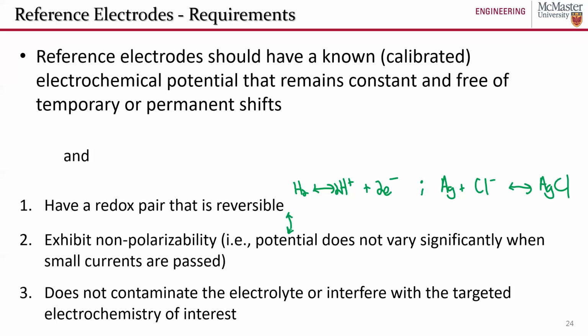Then you also want a reference electrode that is not going to contaminate your experiment. It's not going to contaminate your electrolyte. It's not going to contaminate your working electrode. It's not going to interfere with the targeted electrochemistry of interest. So say, for example, you're using a silver chloride reference electrode, and some of the chloride ions leach out of your reference electrode into your electrolyte. For something like platinum, chloride ions can interfere very strongly with some of the electrochemistry. So you just want to make sure that whatever reference electrode you're using is not going to contaminate your experiments.